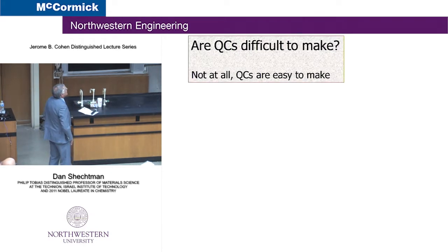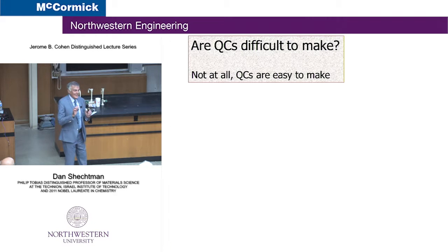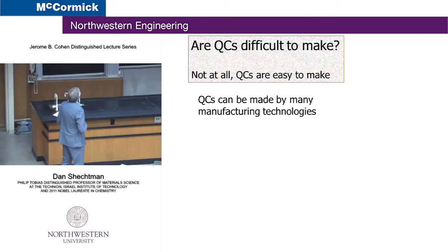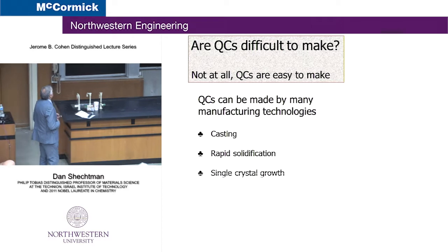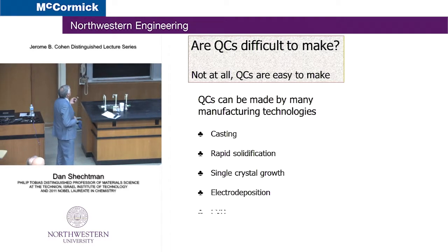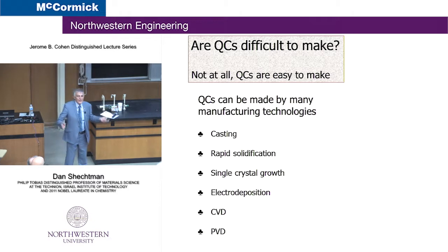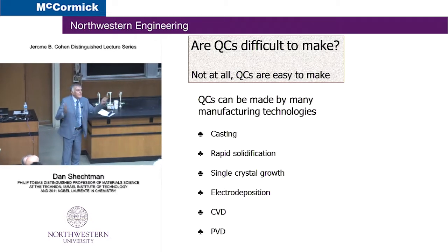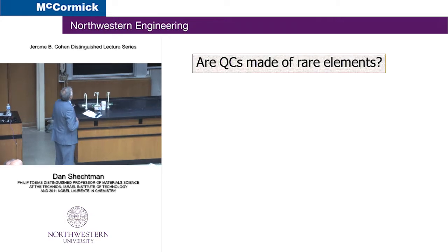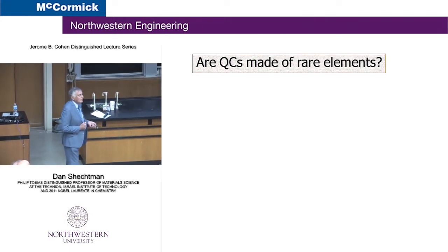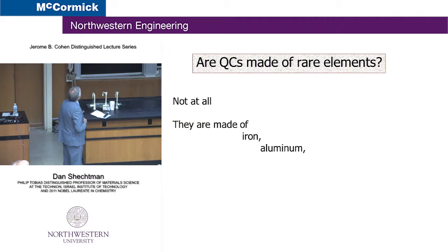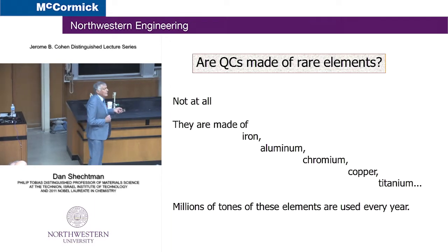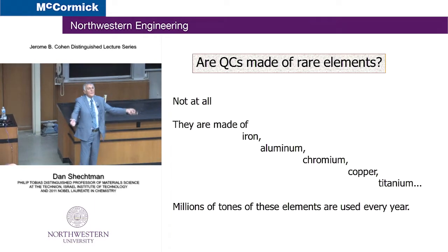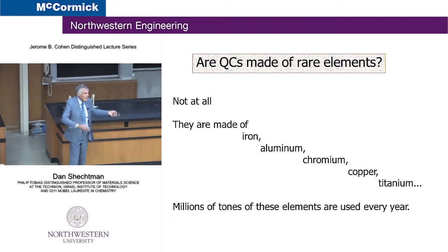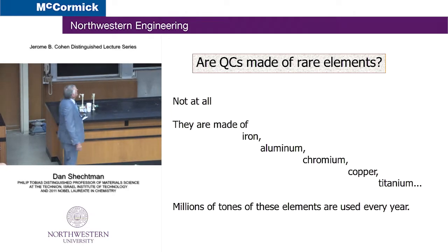Okay. Are they difficult to make? And I, with my magic touch, made a few. Not at all. They're very easy to make. You can make them by casting, by rapid solidification, single crystal growth, electrodeposition, CVD, PVD, any method you like, any materials, you make quasi-periodic material. Easy to make. Very easy to make. Are they made of rare elements? Not at all. They're made of iron, aluminum, chromium, copper, titanium. Millions of tons of these elements are used every year. These are the simplest materials available, abundant. This is not the reason they were not discovered.